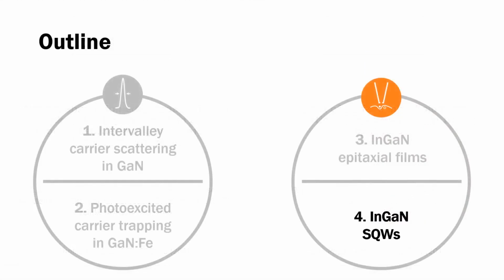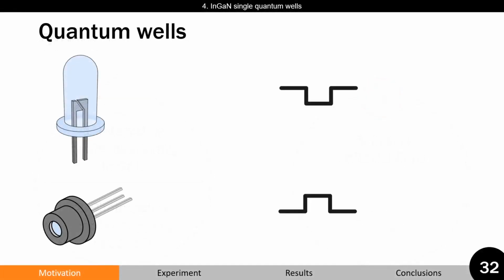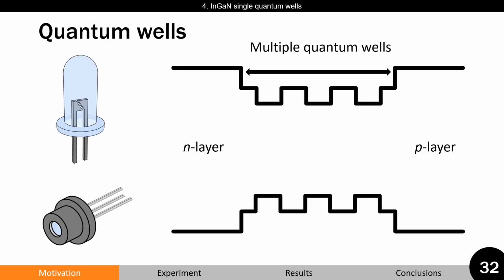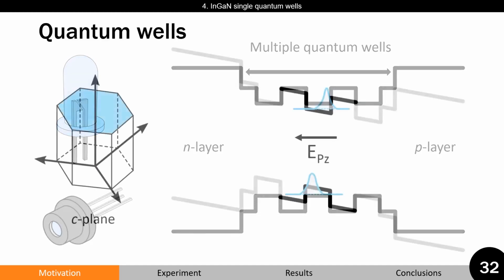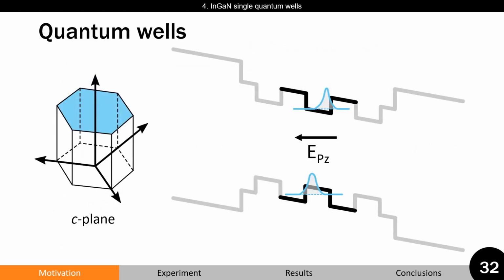In the last research project, indium gallium nitride single quantum wells were investigated. Quantum wells are the building blocks of both LEDs and laser diodes. Usually, they are grown as sets of multiple quantum wells to have larger active volume. Nitride technology is primarily based on the polar c-plane, which, due to the internal piezoelectric field, results in formation of triangular-like quantum wells. One can observe the overlap between wave functions is reduced, hence radiative lifetimes are prolonged.